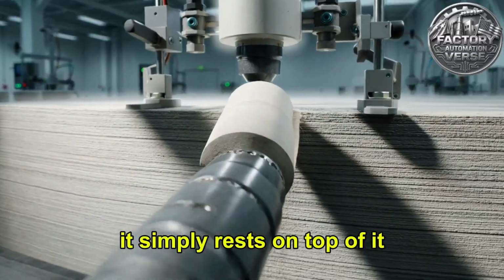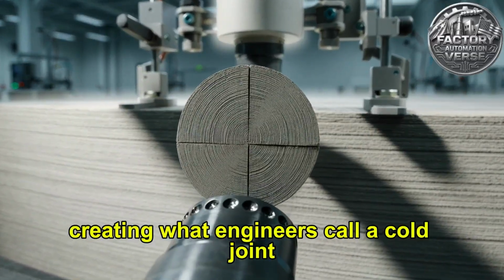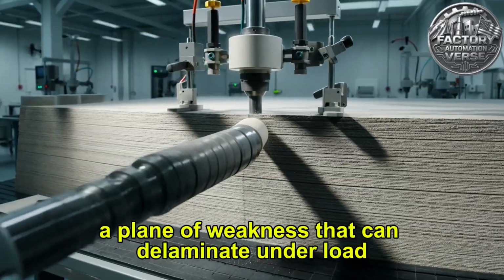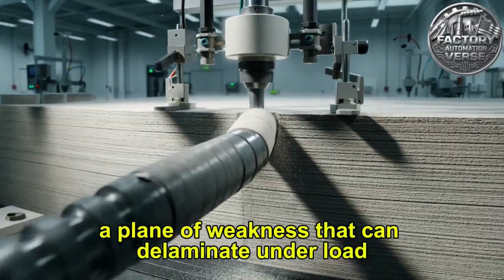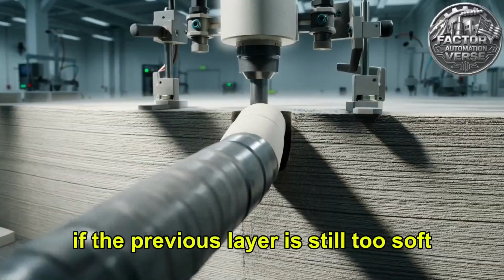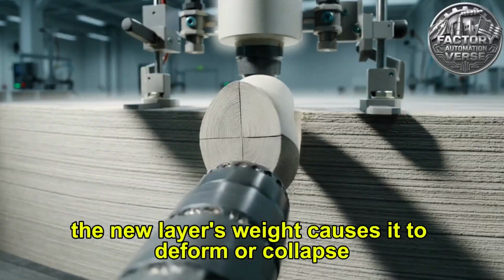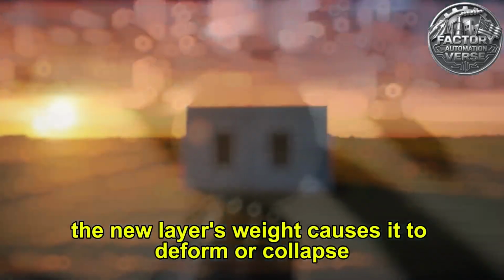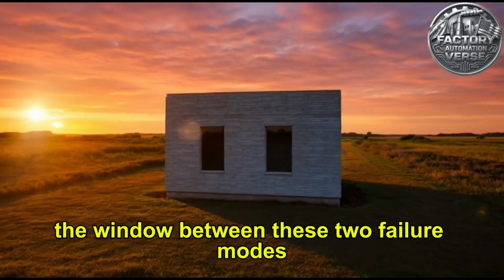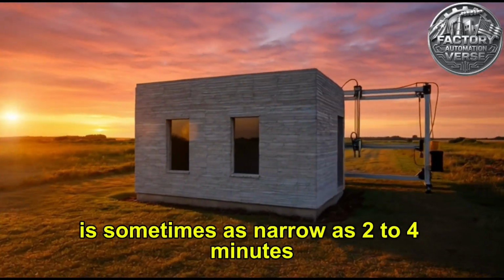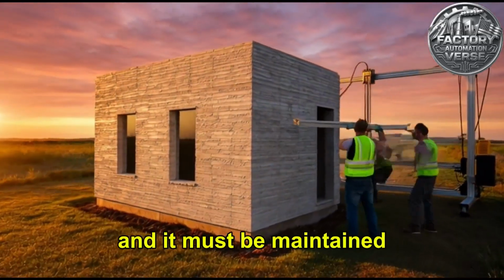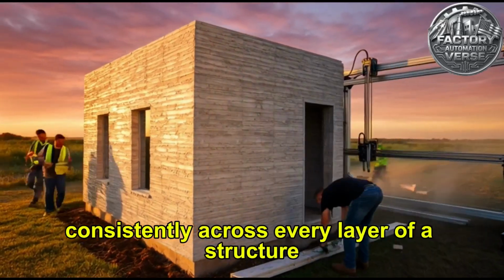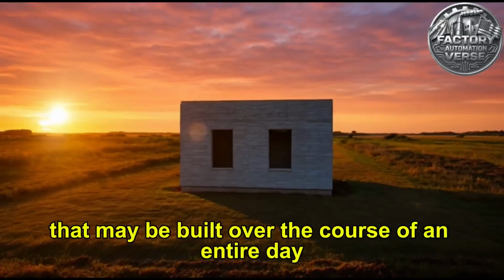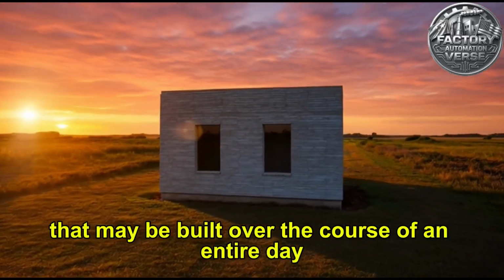It simply rests on top of it, creating what engineers call a cold joint, a plane of weakness that can delaminate under load. If the previous layer is still too soft, the new layer's weight causes it to deform or collapse. The window between these two failure modes is sometimes as narrow as 2 to 4 minutes, and it must be maintained consistently across every layer of a structure that may be built over the course of an entire day.